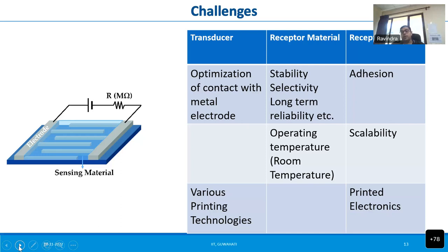That will hamper your gas sensing properties, although it allows you to print very nicely and you will have very good transducers. For example, if you are using silver nanoparticles to print a transducer, you add something to make it viscous, reaching say 10 cP or so viscosity. Then if you print, you will have very good electrodes, with gaps of say 100 micron or so.